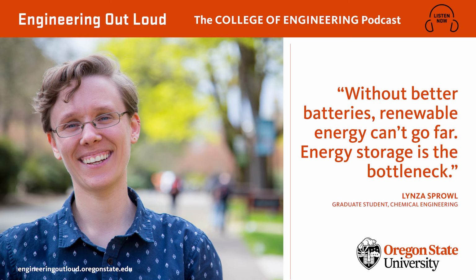But that's not the only problem. As the electrolyte breaks down on the anode surface, it also consumes some lithium. So you have fewer lithium ions that can reach the anode. And so I'm looking at the breakdown of the electrolyte on the silicon surface. If the problem is caused by the electrolyte breaking down, it seems like the obvious question would be, how do you stop the electrolyte from breaking down? As it turns out, that question is just a little bit too obvious, and the answer is way more complicated.